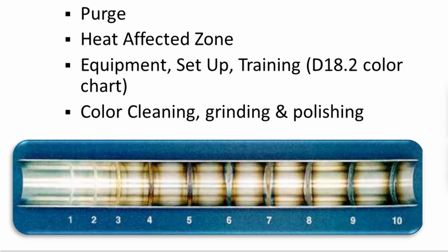And more heat is not good. I mean, there is a good middle ground. AWS covers that, I think, pretty well. Because what you start doing too is you start widening out that heat affected zone. And a lot of people think the weld bead is the most critical corrosion area. It's not. It's the heat affected zone, which are 2 bands right next to that weld bead. That's usually where you see corrosion start to happen.